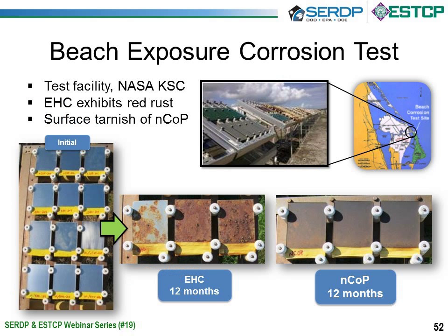To confirm that our results are not artificially affected by an accelerated environment, we then produced a data set utilizing beach exposure testing capability that we have south of Jacksonville at the Kennedy Space Center. These particular witness coupons were tracked by NASA employees for us over a period of 12 months, and reported out every 2 months. A little bit too much for this particular presentation, but in essence, the summary is we duplicated what occurred in the accelerated testing from the previous slide.